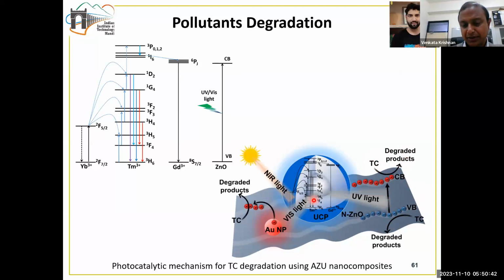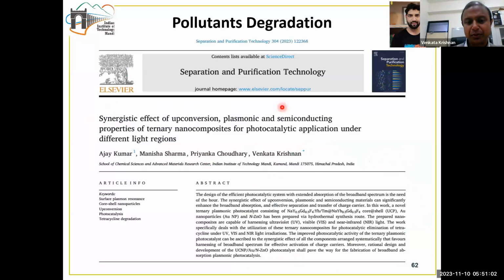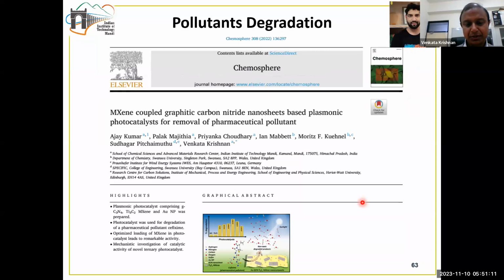On the other hand, the visible light, which is again emitted by the upconversion nanoparticle, impinges onto this gold nanoparticle, and due to the SPR effect, that leads to the promotion of an electron from the gold nanoparticle to the conduction band of this semiconductor, and again those electrons lead to the degradation of the pollutant. And this work was published in the beginning of this year in Separation and Purification Technology with my former PhD scholar Dr. Ajay Kumar as the first author. And subsequently, we have also worked on MXene-based material.